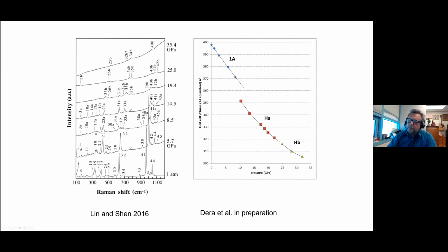This is from a paper that was published in 2016 and used Raman spectroscopy. So in this paper, 2 discontinuities in the pressure behavior of Raman modes were reported, but because diffraction was not part of this experiment, the structural mechanism responsible for these 2 discontinuities was not well understood. So our diffraction experiments performed with the same technique by loading multiple single crystals into a diamond anvil cell and collecting single crystal diffraction data, revealed, just like this Raman experiment, 2 discontinuous phase changes.